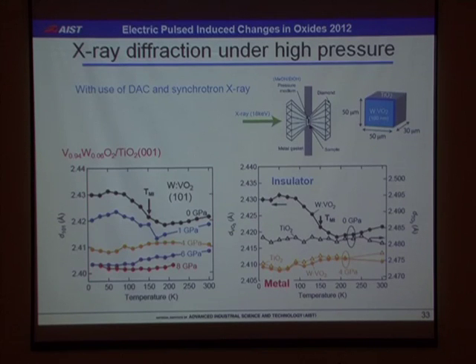So we also investigated XRD under high pressure with a combination of diamond anvil cell and the synchrotron X-ray. The film is patterned like this size and put in the diamond anvil, and we measure X-ray. And this is the lattice constant versus temperature. At ambient pressure, it shows the structural transition, represented by this increase of lattice spacing. And that is not observed at high pressure. Here, the lattice constants of VO2 and TiO2 are plotted. At ambient pressure, as I told you, it shows structural transition, but that was not observed at high pressure. This means the electron-doped VO2 has a rutile structure in this temperature region.